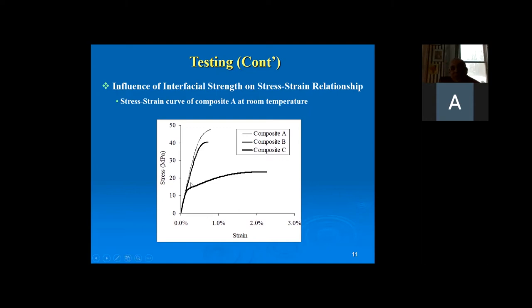However, if we use a debonding agent, the matrix is unable to transfer the strain to the particles. So essentially, we are getting the response of a polymer with almost no particles, because this is composite C. In composite C, we said we are using a debonding agent. So we are making sure that the particles do not bond to the matrix. So as a result, there is no interfacial strength. And polymer is, of course, a very ductile material. However, the ultimate strength went down significantly, but the ductility increased by orders of magnitude.